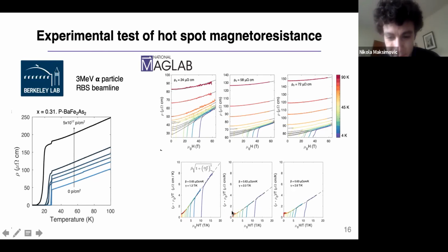I can tell you why this is happening. This is happening because the curvature of these curves is changing slightly. It's actually not perfectly T-linear. So especially in disordered samples, at high temperature you start to see this spoon shape. I can't explain to you why in particular you start to see deviations at high temperature in the context of this model. But it's a reflection of the fact that the temperature-dependent resistivity is changing slightly. Okay. Thank you.